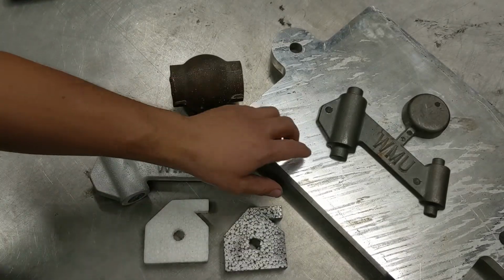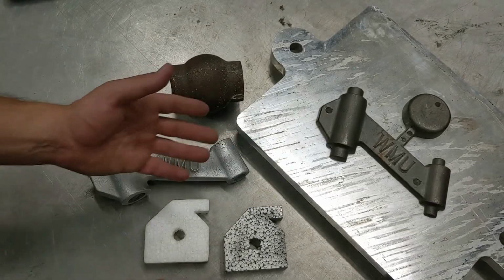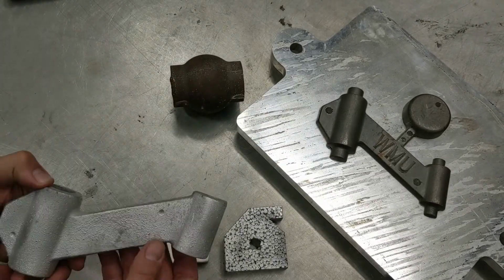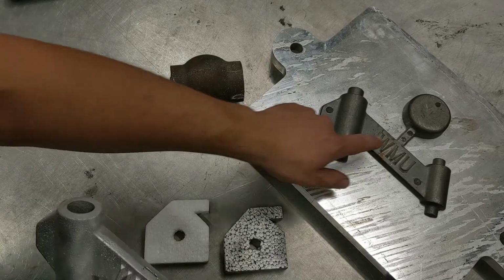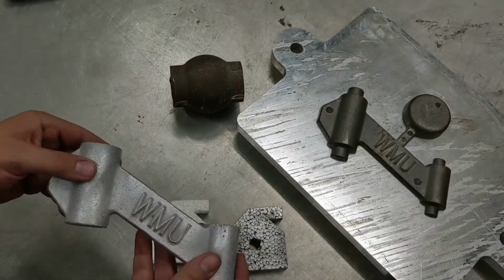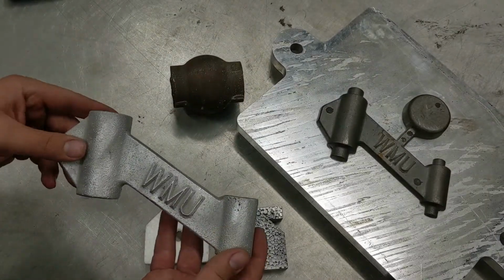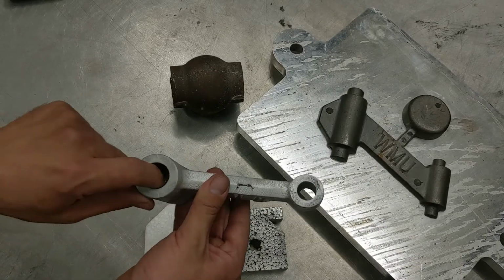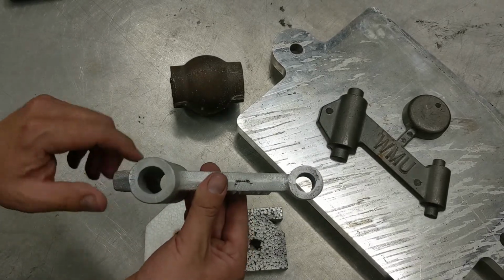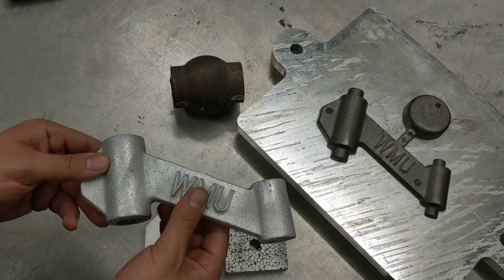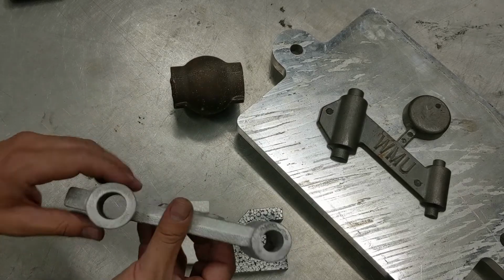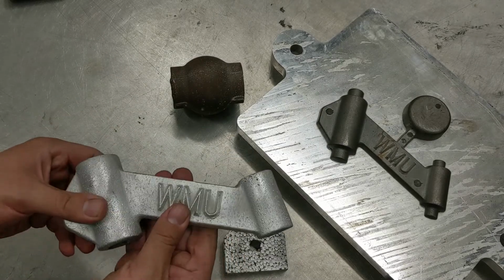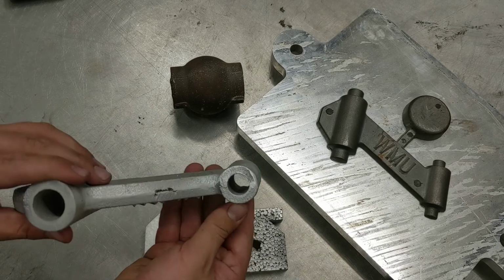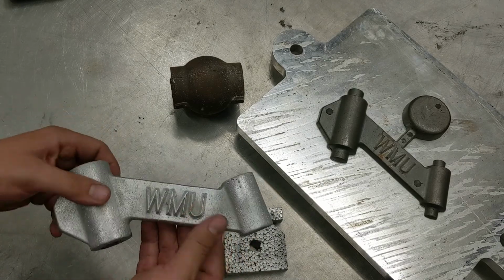So it just so happens that this pattern is used here at Western for research in shrink defects. So this gate and runner system is actually replaceable to turn that defect on and off. But we see really good surface finish here on the inside of our core sections, and that's exactly what you would get on the inside of your engine blocks and cylinder heads when the green sand system is used to make those types of products.